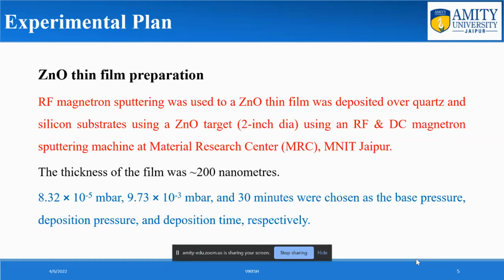Firstly, Rutherford backscattering spectroscopy. RBS is an effective technique for estimating material thickness and compositional parameters. This was accomplished using a 3 MeV helium plus 2 beam. The spectrum was simulated using the Rutherford Universal Manipulation Program, RUMP, to determine the thin film thickness. The film thickness was calculated to be around 200 nanometers with the RUMP software.